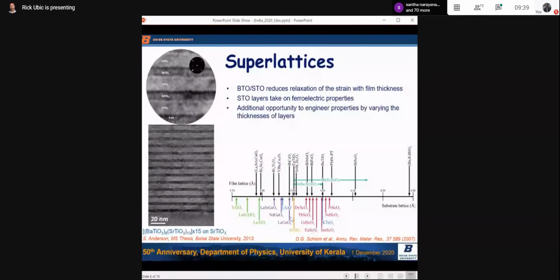This is a specific example from one of our master students several years ago. He was growing barium titanate and strontium titanate, two different perovskites together, a few atomic layers of one, a few atomic layers of the other, in these layered films like this. And the idea is that barium titanate is ferroelectric, has a certain kind of electrical properties. Strontium has a different kind of electrical properties.